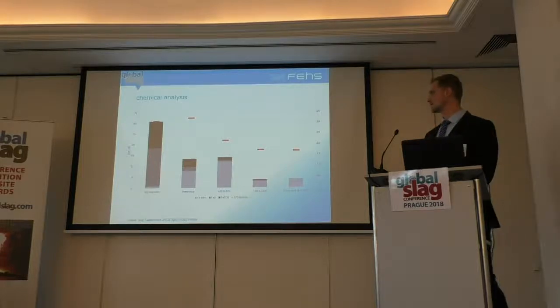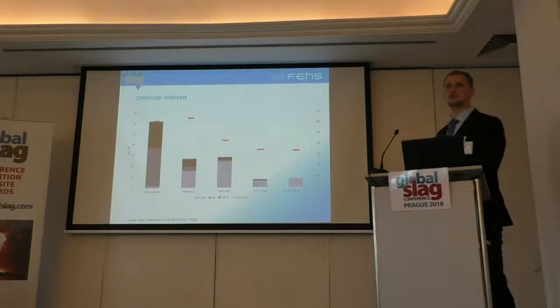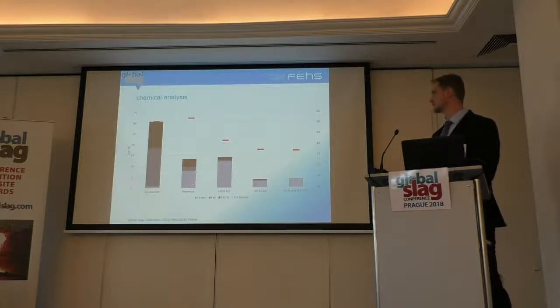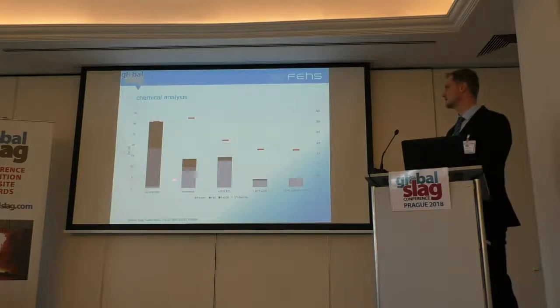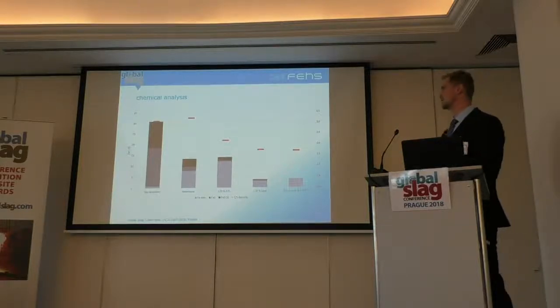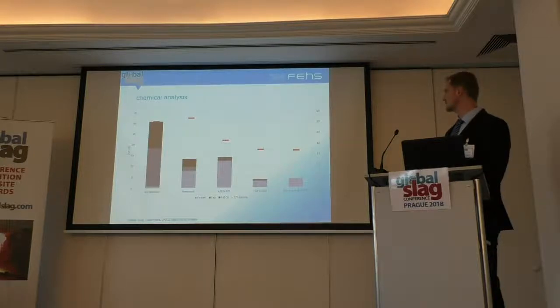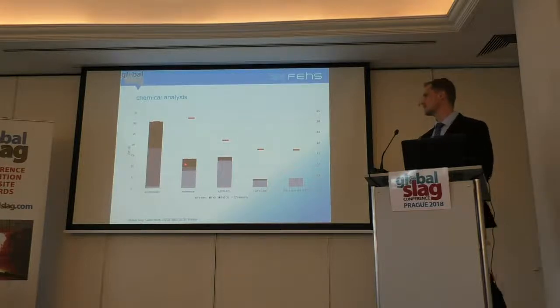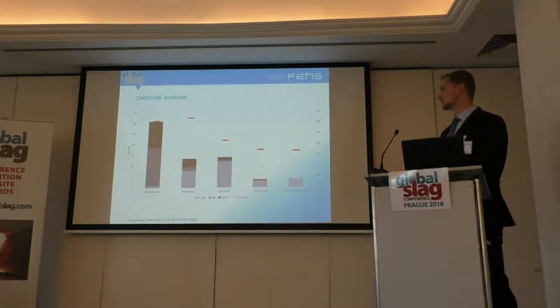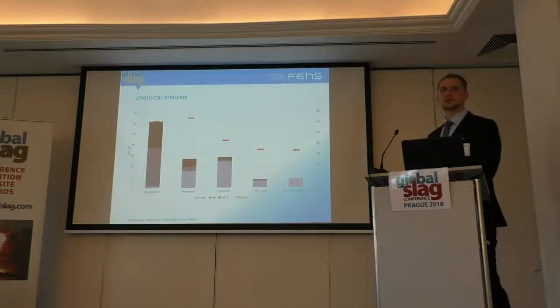Here the columns are the sum of the different oxidic states of iron. So the silver is metallic iron, then the gray one is FeO, and the black one is Fe2O3. So we are able to separate these oxidation states. The red lines are the CaO/SiO2 basicity. It's here on the right side, and you can see due to the simple carbon reduction, we don't really change the CaO/SiO2 basicity, but we reduce the iron content. But there's still a lot of iron oxide remaining in the slag.